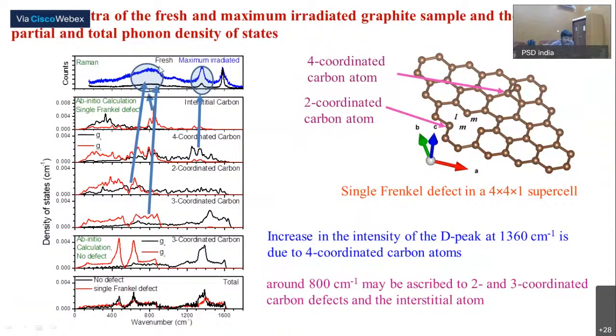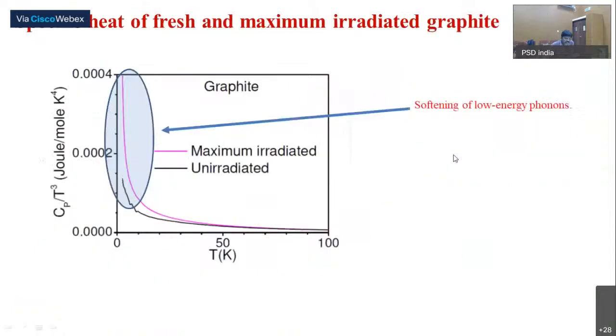So, we can see that this increase in intensity at around 800 centimeter inverse is due to the interstitial atom as well as the 2 coordinated and 3 coordinated atoms, and this increase in intensity of the defect peak is due to the 4 coordinated atom. And this is the specific heat, and we see that in the maximum irradiated sample the specific heat is slightly higher at low temperature. This is because when we irradiated, there is a softening of the mode, and this softening of the mode gives rise to an increase in the specific heat at low temperatures.